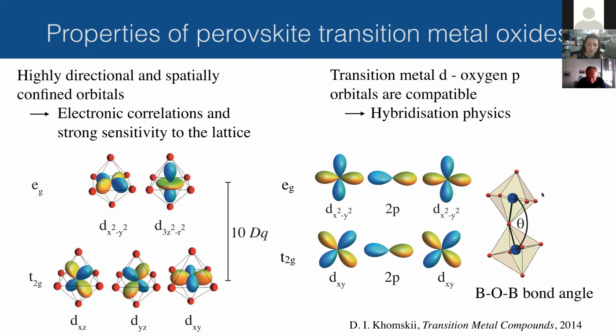So what's important here is, of course, how well aligned the oxygen p orbitals and the nickel, what we will talk about later, or the B site orbitals, how well they are aligned in space. So you can characterize this with just the bond angle. Here we call it the BOB bond angle, from the B site cation to the oxygen to the next B site cation, and you have an angle which, in the perfect cubic perovskite, like strontium titanate, would be 180 degrees. And then for almost all other perovskites, it is less than this.